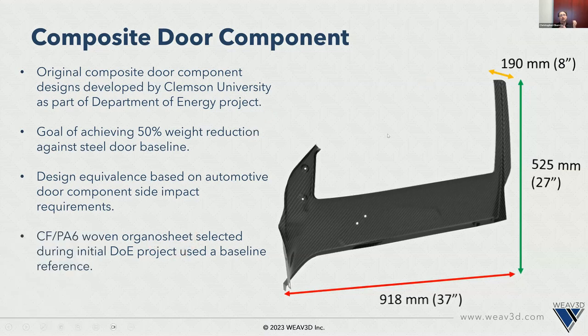that I mentioned earlier. This was originally developed by Clemson Composite Center as part of a Department of Energy project that they received with the goal of redesigning a steel door into an all-composite door with a 50% weight reduction. Their original design concept called for using a carbon fiber nylon 6 woven organosheet. They were going to mold this organosheet and then trim out all of the window areas and things like that. As you can imagine, if this is your part here on the right, starting from a large rectangular blank, you're going to have a lot of waste.